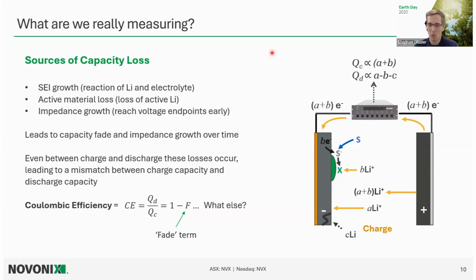So to describe why Coulomb counting is really important, I'm going to talk about different failure mechanisms, different degradation mechanisms that happen, and what that means for the electrons that we're counting through this battery tester. We're all quite familiar with measuring capacity loss. This is where lithium is consumed from SEI growth or active material loss. Even impedance growth can affect our capacity loss.